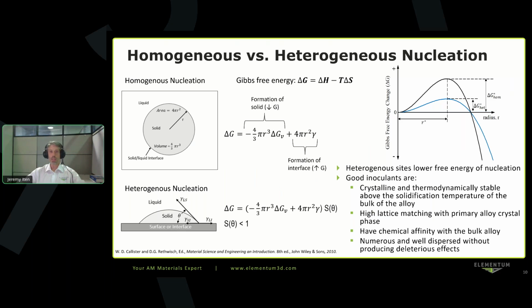In general, you want these to be good inoculants, crystalline, thermodynamically stable above the solidification temperature of the bulk alloy. You want high lattice matching with the primary alloy crystal phase. So having lattice matching will help with allowing the primary phase to solidify off of those initial inoculants. You want chemical affinity with the bulk alloy. It needs to wet, it needs to have some affinity. And you want numerous and well dispersed without producing deleterious effects from having the wrong elements in your alloy.